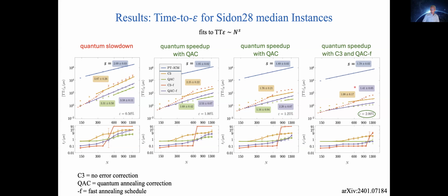And finally, at an optimality gap of 2%, so this is a generous allowance for not finding the ground state. Unfortunately, we're not able to establish an optimal anneal time at all for QAC. So that's why there's no slope reported for QAC here. But for C3, for the three copies, the result is significantly better than for PT-ICM. And also QAC fast, the fast schedule version of QAC, is also beating PT-ICM. So these are all encouraging.